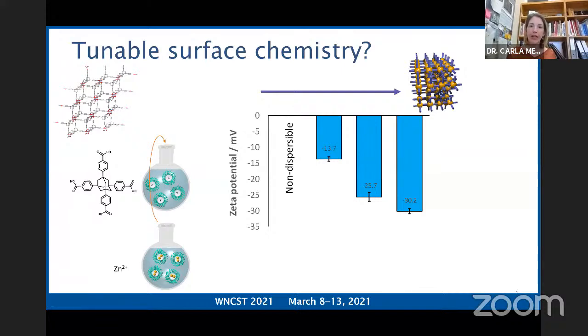So again, another advantage of making these MOFs on the nanoscale is that we can disperse them, and we can tune the surface chemistry. So we can go from nanocrystals that are non-dispersible to those that are very dispersible and with a very negative zeta potential at high pH, indicating that the surface of the nanocrystals are terminating at the ligand rather than terminating at the metal ion.